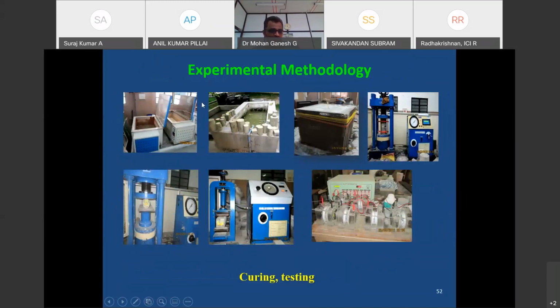And this picture shows the experimental methodology. This I have already shown: alternate wet and dry tank, curing tank, accelerated curing tank, and this is our curing tank. This is a setup we have used for finding the rise in temperature. If we place the concrete or high volume fly ash concrete, how much temperature or how much heat is generated, we found with a thermometer or with the thermocouple. And for finding the compressive strength, UTM, and split tensile strength we have done. And for RCPT, this is for RCPT.